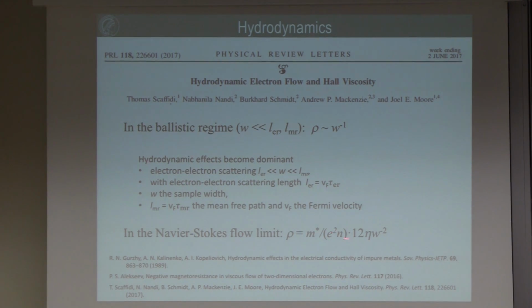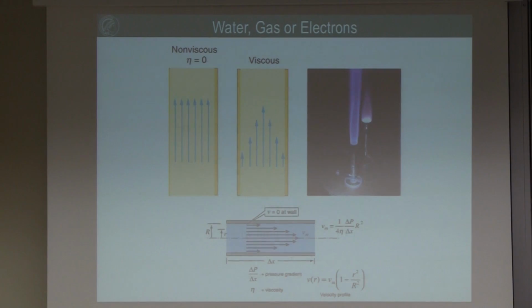So then we thought, what should we find if we measure now the width dependency? So this is this very nice paper from Joel Moore with Andy, where they even told us, okay, don't bother, because this compound shows a rho dependency of 1 point something. So we should find a rho dependency of the width to the square, because this is really the Navier-Stokes flow limit, while this is still the ballistic regime.